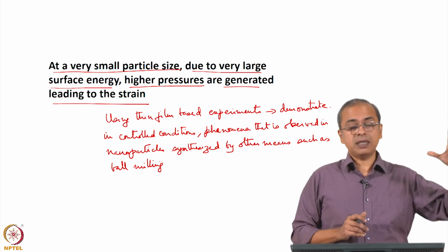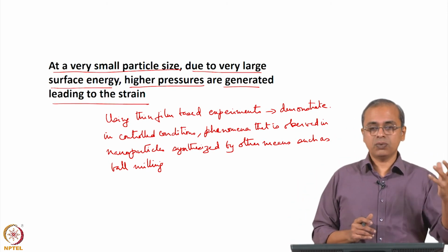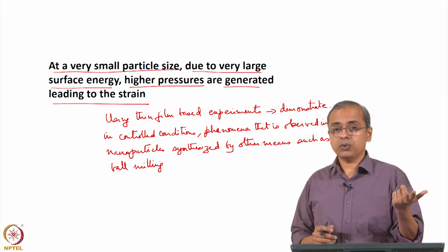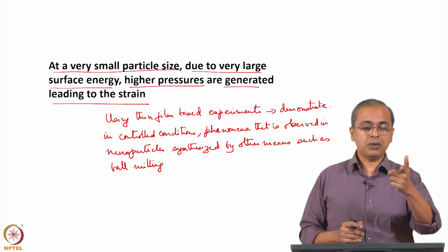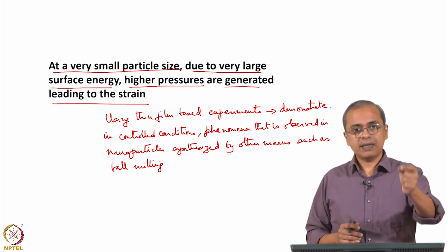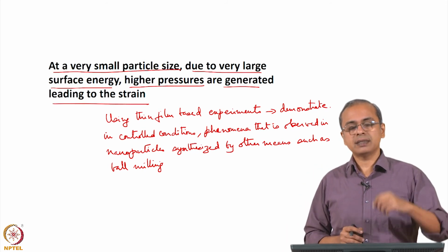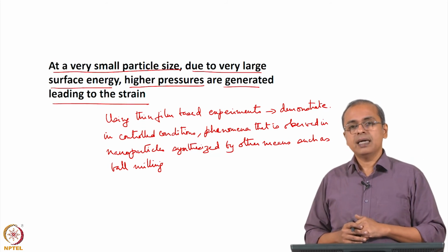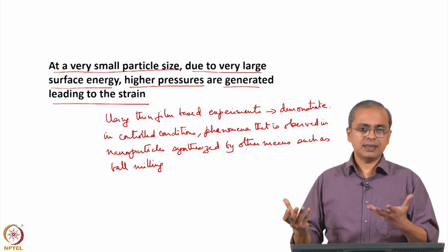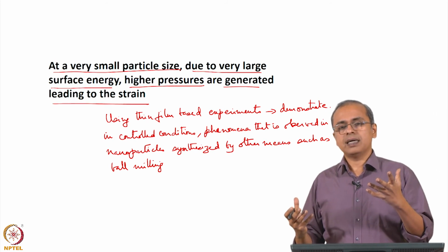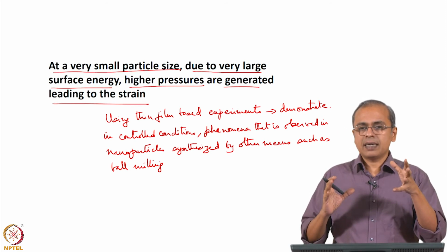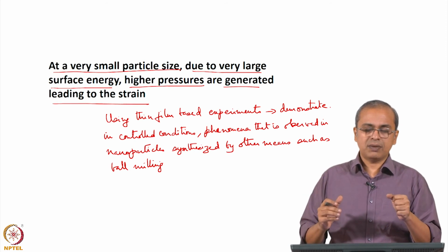So, ball milling gives a different kind of conditions to the particles. They are being hammered, they are broken down, but maybe it could introduce impurities. You are already talking of a nanoscaled material. In that, even if you have a few atoms of impurities, then that is a significant percentage of impurities, and you may have variation in sizes. You may not have enough control to say that you got only this particular size. So, you have those peculiarities associated with it.